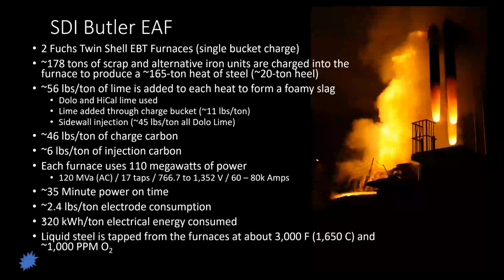With the hot metal, we end up around 320 kilowatt hours per ton. Our hot metal from our submerged arc furnace is only about 7% of our scrap mix, so it's not a large player. If you say 178 ton scrap charge, that includes about 15 tons of hot metal that we pour in, so it's a relatively small percentage—not like 20% of our mix or something.